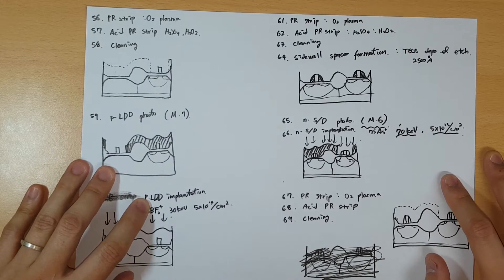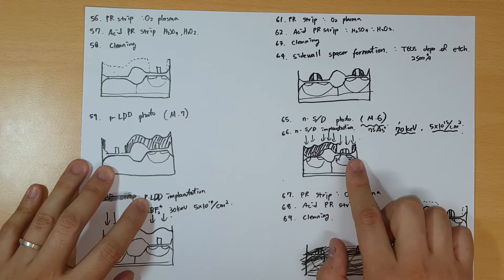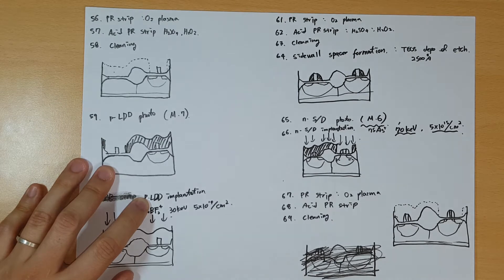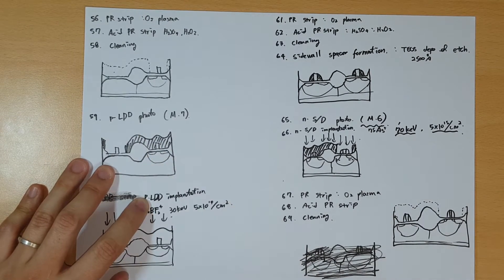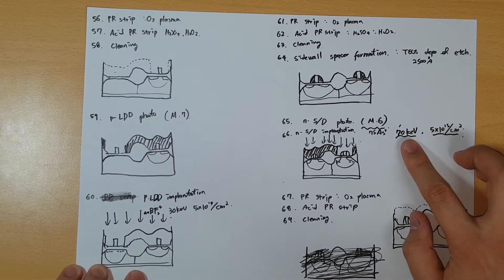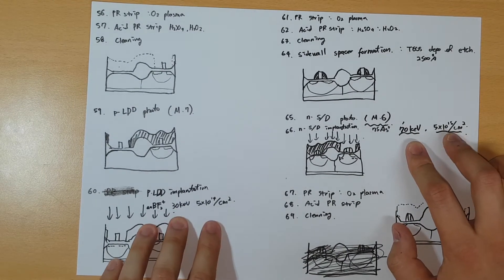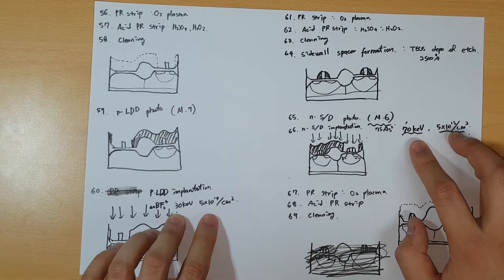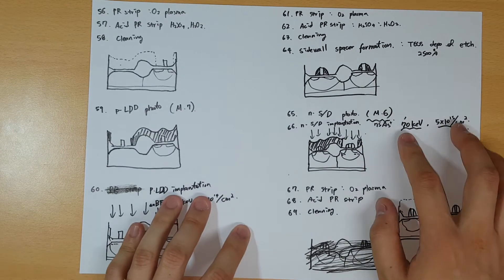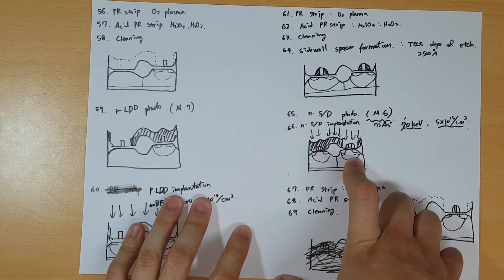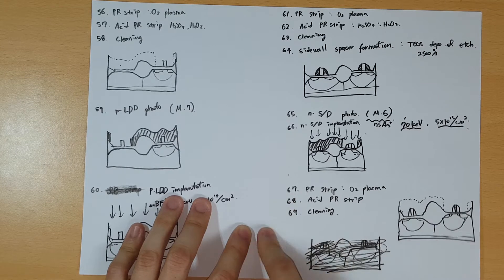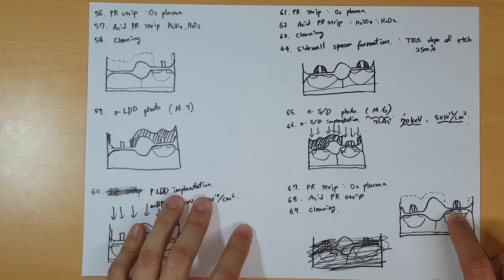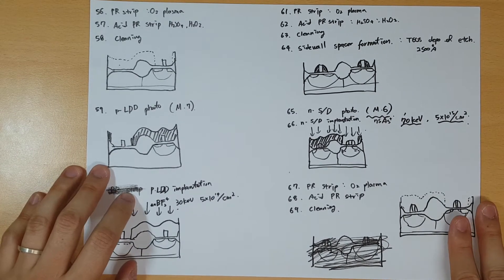Next you do the source drain photo. This one is the actual source and drain. The former one was the low doped drain as you can see. In this step, the concentration and energy is even higher than the LDD process. It was like 30 and something before, but this has higher concentration and higher energy which goes inside under the LDD layer. Then you do the typical cleaning. Now you have small LDD layer here and actual source and drain on this side.